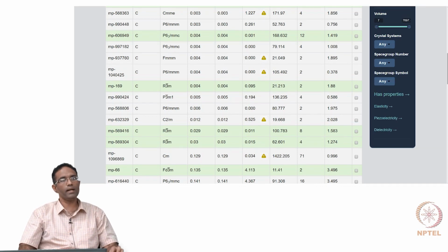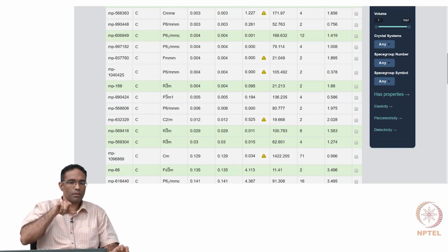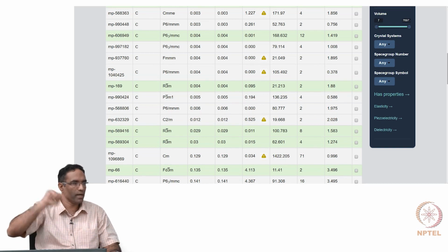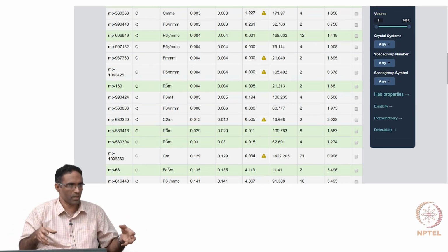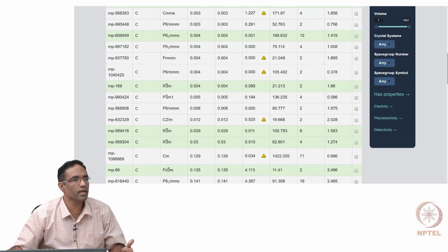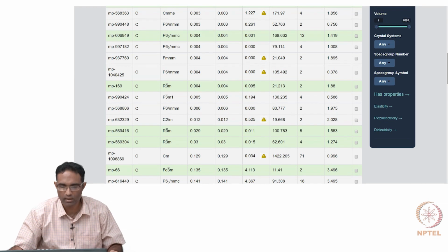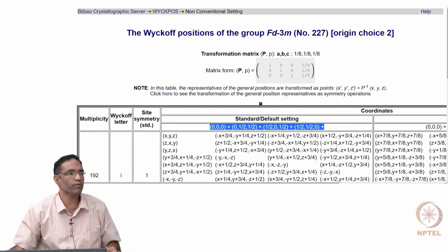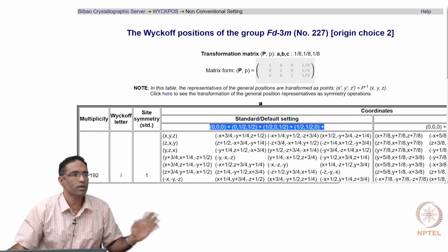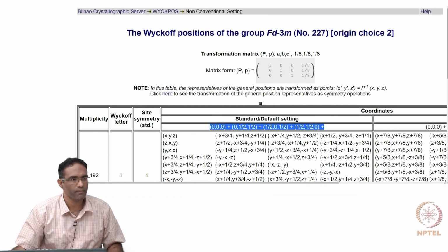Okay. So, other things: the reason I wanted to highlight this diamond structure is that sometimes you will find only two lattice vectors or two basis points, but to each of them you will have to add those centering operators in order to get the required multiplicity. Whenever you see any centered lattices, just A, F, C, I, you will find these things on top, to which you will have to add each of these components, and after adding, make sure that they are not greater than 1 or less than 0, so that you can bring them back into the unit cell. Is that clear?